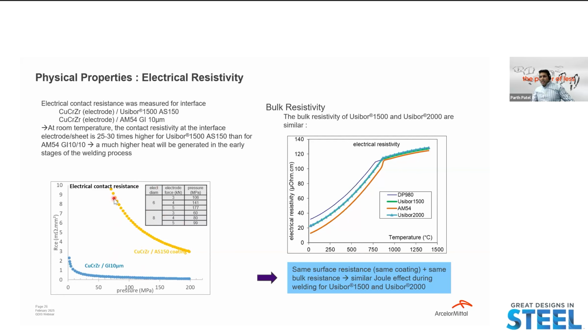So it has good electrical contact resistance, and that's why it will generate more heat. While if you look at the bulk resistivity, which is for the base metal, Usibor 1500 and 2000 are very similar - not that much difference. So the key message here is your coating really matters, your hot stamping process really matters. For PHS, if there are any welding issues, you may want to look at how your coating looks, how your IDL looks, and that's more important. But the key message for our material, Usibor 1500 and 2000, is that it's very similar despite having different carbon percentages.